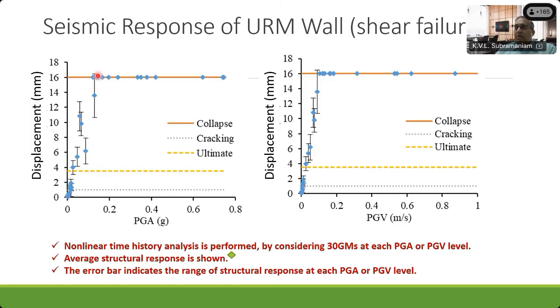So it doesn't take a whole lot of ground acceleration to fail these walls, which would otherwise exhibit a shear type of failure under static loading. All it would take is a very small amount of PGA of around 0.1 or so to produce failure in these walls. Same thing with the PGV.